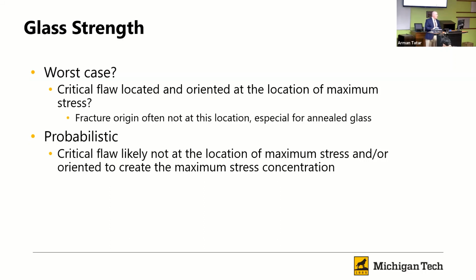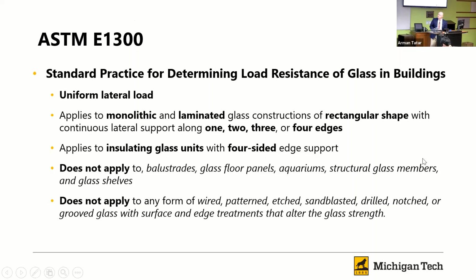We also find that not only the magnitude of the stress, but also its orientation, affects this. If our flaw is oriented such that the tension runs parallel to the flaw, then we're not changing that flaw tip. It has to be perpendicular, and anything that's off angle from that is going to lower that stress concentration. So where we get into that is, can we use a probabilistic method?